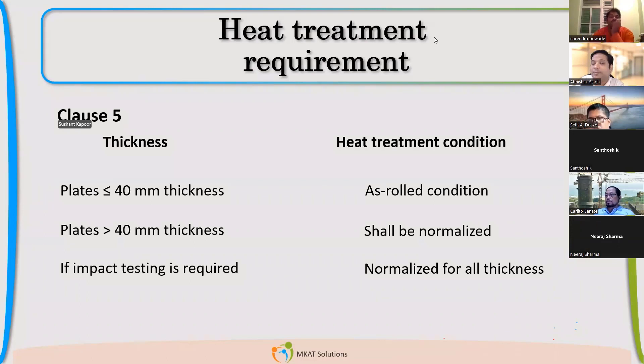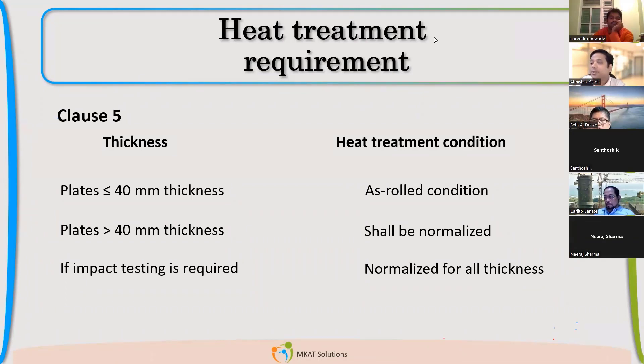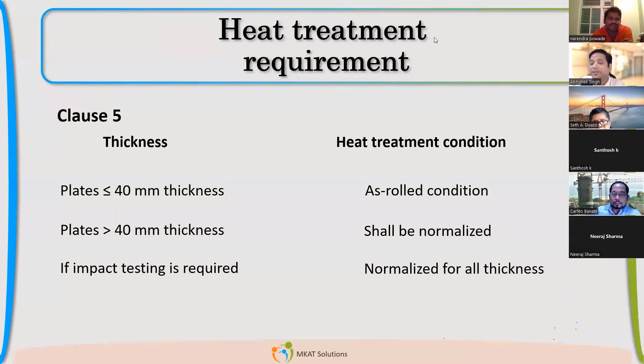This is a very important point you should remember. Less than 40mm, we can order as-rolled. Greater than 40mm shall be normalized. And if there is an impact testing requirement, then whatever thickness you are using, it has to be normalized, irrespective of thickness.